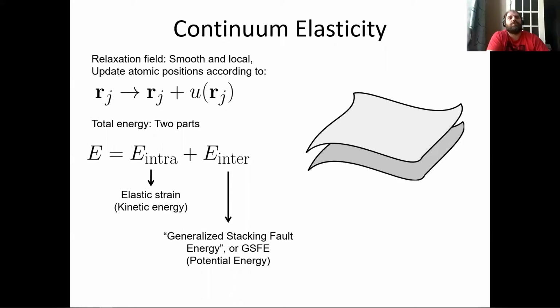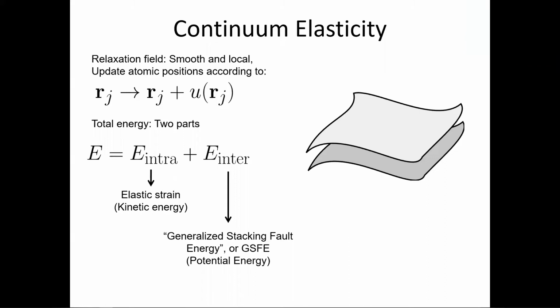Okay. If we have the band structure with the gap, could the electrons contribute to the deformation? I mean, they do in some way, but that should be captured. We're doing a linear expansion of the energy. So we're basically assuming that the strain energy is captured by a quadratic term that depends on the shearing or the isotropic expansion, and that's it.